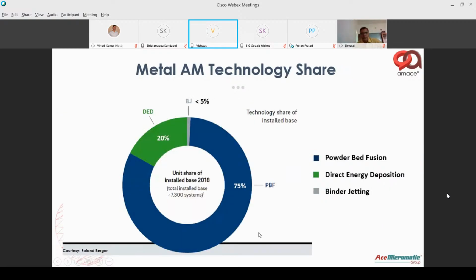In the metal 3D printing process, we discussed powder bed fusion, PBF. As I explained, about 75% of the printing that happens in metal uses powder bed fusion technology. The other one is DED, which is directed energy deposition or direct metal deposition. In this case, metal is fused through a coaxial laser and metal jet. Powder metal is sprayed using a nozzle onto a plate. This is similar to 5-axis machining. If you've seen 5-axis machining, you can imagine that instead of the spindle cutting material, you have a nozzle body spraying metal with a laser surrounding it.